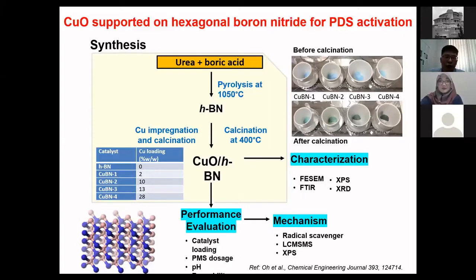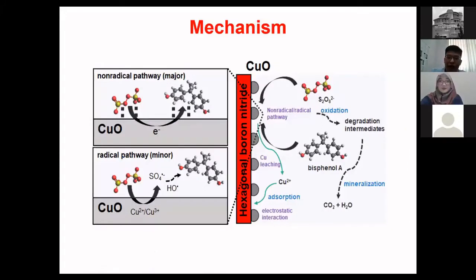Okay? So another thing that we like about hexagonal boron nitride is that it is also a copper adsorbent, which means if you have copper leaching, right? If your copper somehow interacts with the peroxydisulfate and it leaks out, the boron nitride can adsorb the copper back to the catalyst. So this is how it works.